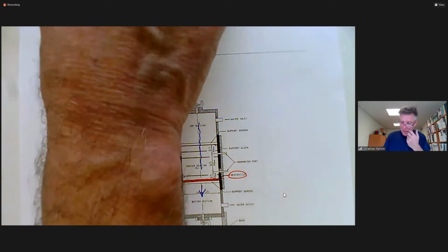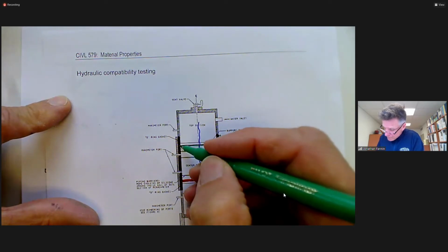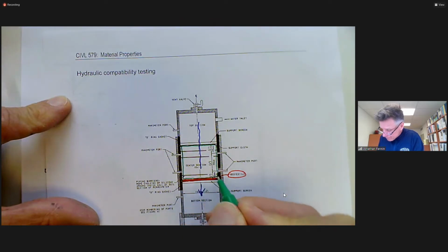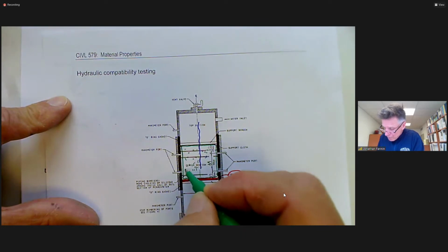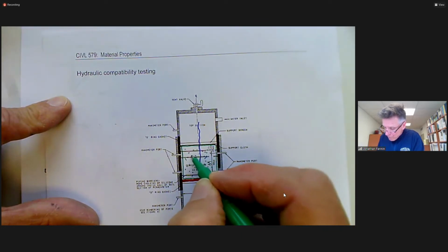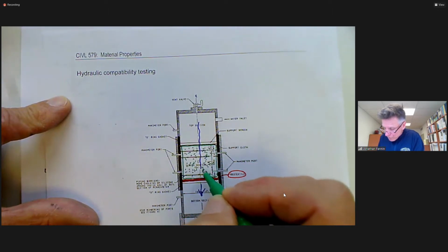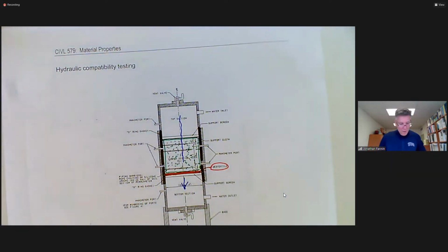But what then if we were to place soil? A soil specimen. What if we were to reconstitute a soil specimen and actually flow the downward unidirectional seepage flow across that? That's what's referred to as the ASTM gradient ratio test.